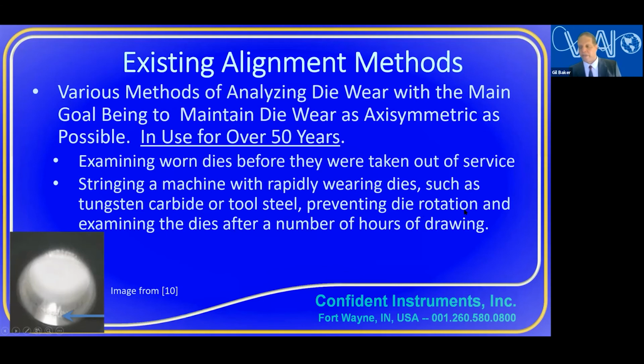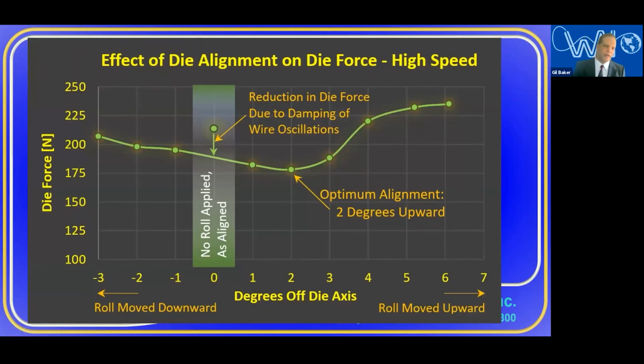Now, again, I would say you want to prevent the die rotation, and this would be just drawing over a few hours. After those hours of drawing, you examine the die and see if there's a symmetric deformation zone. Now, again, with cast, there'll never be a symmetric deformation zone, but you can adjust the alignment such that you can improve the deformation zone. In the article, we go into a high-speed alignment optimizing experiment. In that experiment, we determined that we wanted 2 degrees off the die axis in the upward direction. In other words, here's the capstan and the wire is coming in a little bit upward. And again, I'm not going to go through all this, that's in the article.